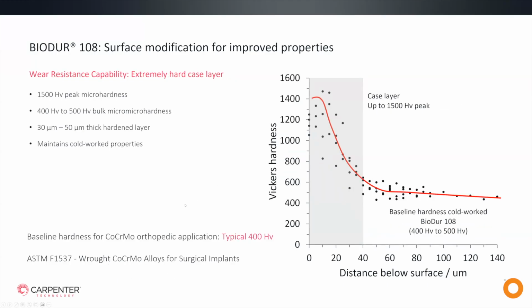However, I think this slide does a bit better job of explaining the material and the potential of the nitriding process. So first, again, the surface nitriding of BioDur 108 is performed at lower temperatures, and this is purposeful, right? It preserves the cold worked microstructure and the underlying strength, the underlying toughness, the grain size, the grain flow.